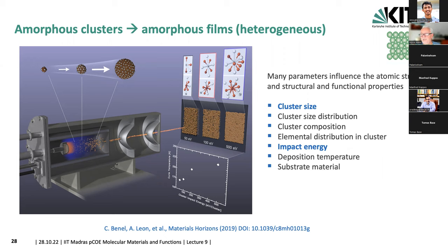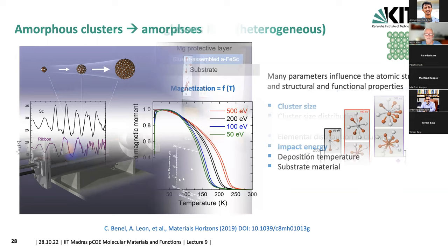We have also done EXAFS measurements to learn about the environment of the iron and of the scandium atom. And what you see at the top here is the atomic environment of iron and scandium, scandium at the top, iron at the bottom, for the different impact energies, where you can see that the number of nearest neighbors is different, and also the configuration is different. And this configuration for the 500 eV is basically identical to what we find also in a rapidly quenched material from the molten state.